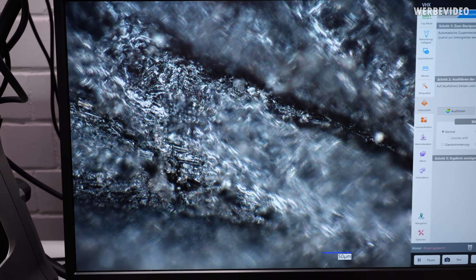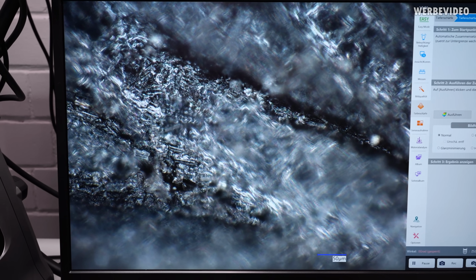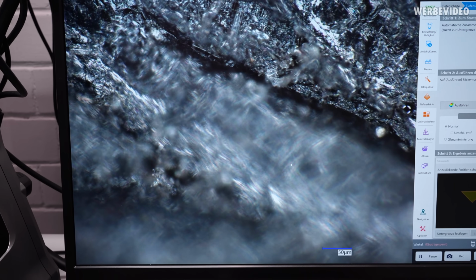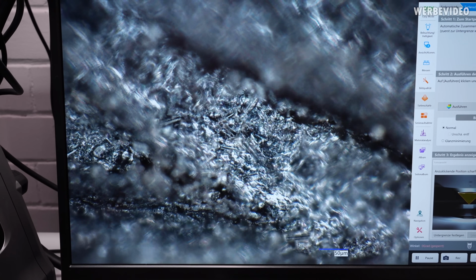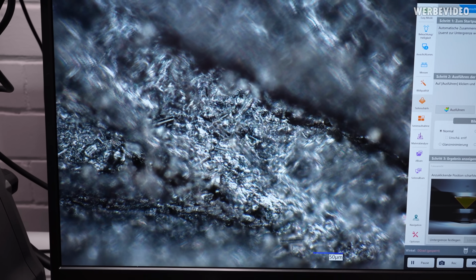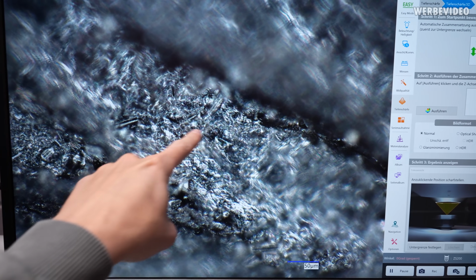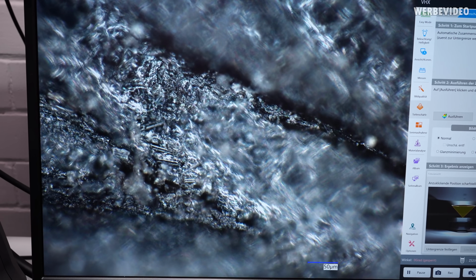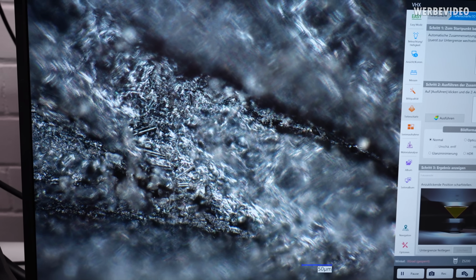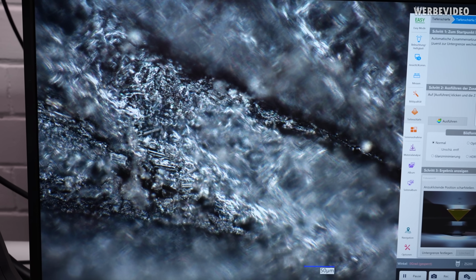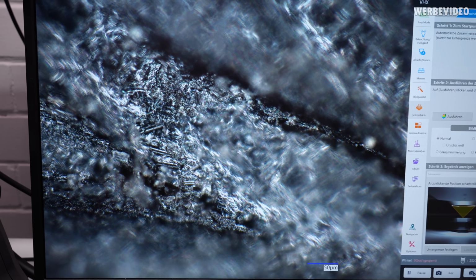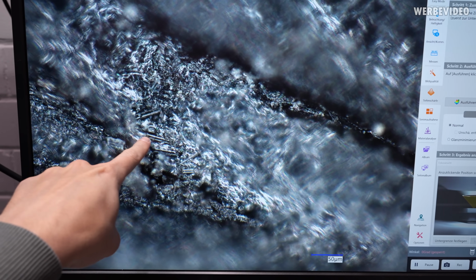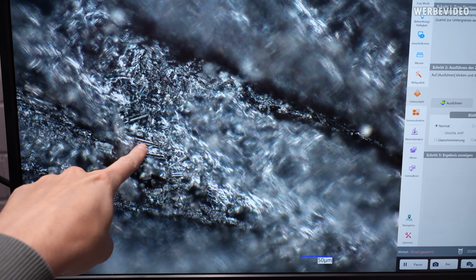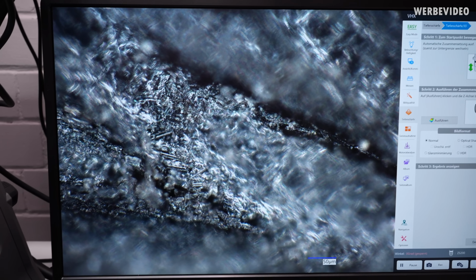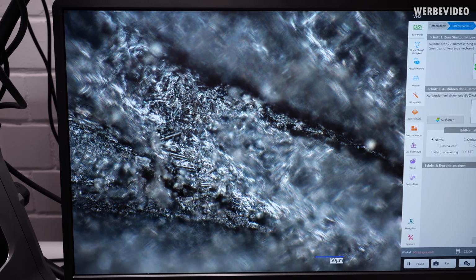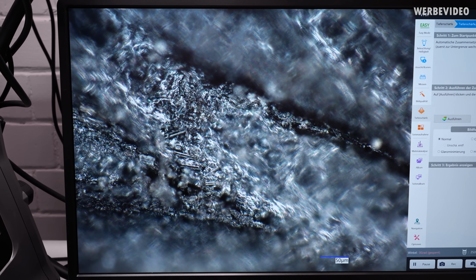Now you might ask yourself the question, why would that now make sense? For this, I switched back to the normal microscope and scratched across the surface, and you can see those round shapes right here. And then it's quite obvious that this is just a fiberglass reinforced polymer. And during the material analysis, we probably just hit one of those fiberglass particles, which mainly consist of silicon. And that just shows that you also have to correctly interpret what you're actually looking at.